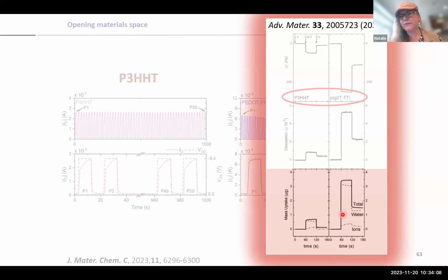And you immediately see the problem when you have glycolated systems, glycolated side chains, or I should actually say ethylene oxide to be in agreement with IUPAC. You have massive mass uptake, and that leads to failure. And as mentioned, this was nearly impossible to measure actually with PEDOT:PSS because the mass uptake was so drastic. And the nice thing is, actually, we measured that in Sahika's lab in KAUST. We can distinguish what mass uptake is contributed with water. So these are these dashed lines, or ions, these dashed dotted lines.